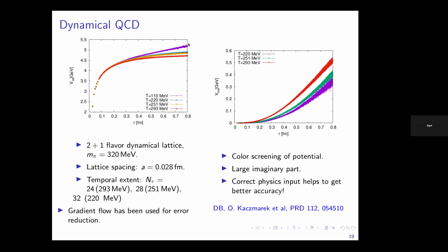Have you seen that in your lattice data? No, it's very difficult to go to that region with these lattices. Already it is showing up a little bit at 0.8, right? Yeah, but up to this point we cannot, because one thing is that the pion mass here is not actually physical, it's actually 320 MeV. So you may expect it not to happen exactly at 1 Fermi, but at a little bit higher distance.